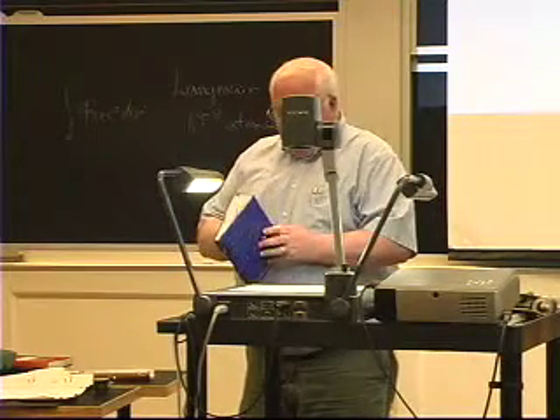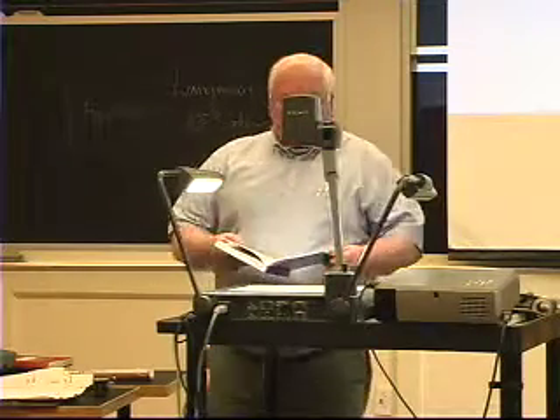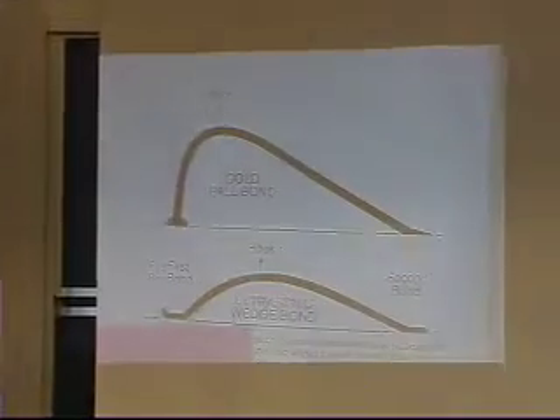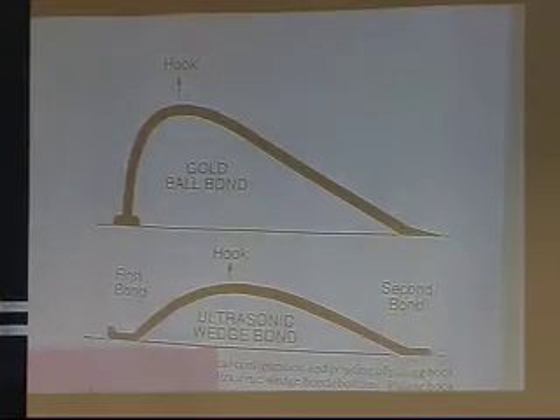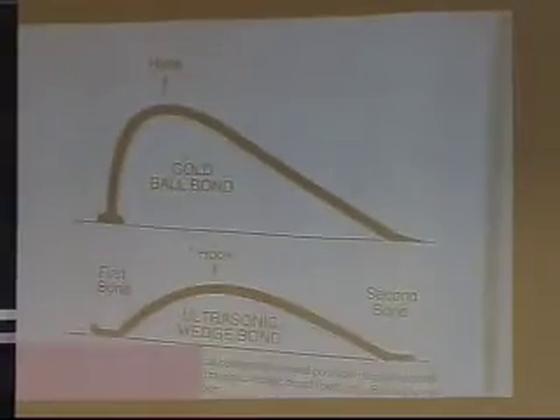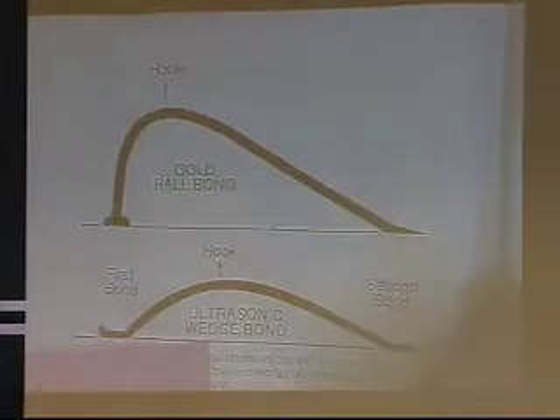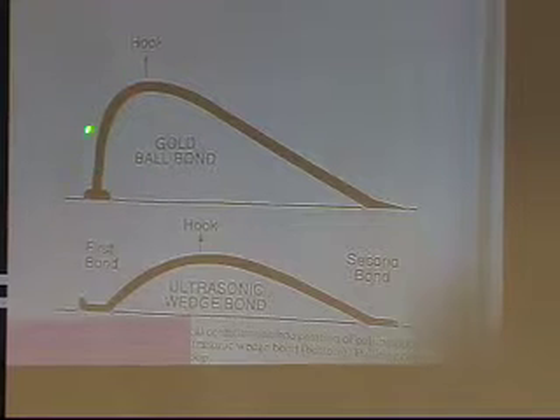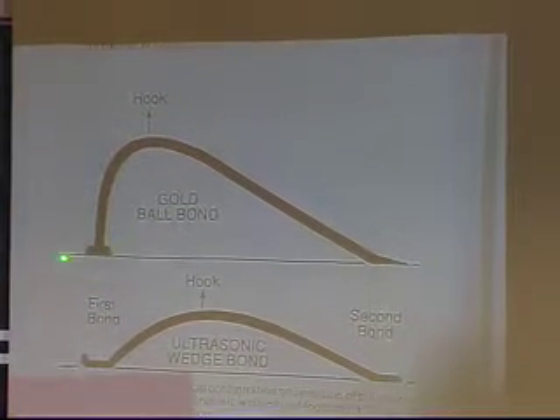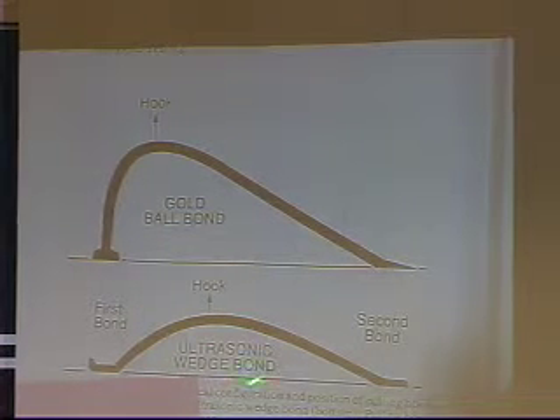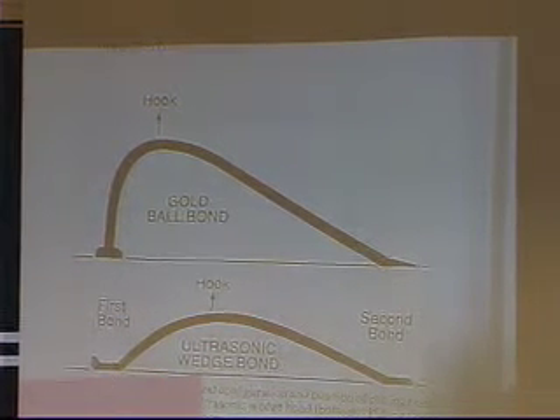Cold welding is used a lot more than a lot of people think. In fact, so far as I know, there are probably more cold welds made than there are virtually any other type of weld, because most computer chips have very fine wires, typically gold, sometimes aluminum when they're trying to save money. The wire diameter is typically about 25 microns, 1/1000th of an inch in diameter, and they make a thermocompression bond to the pad of the semiconductor chip, or they make an ultrasonic wedge bond to the surface of the chip.